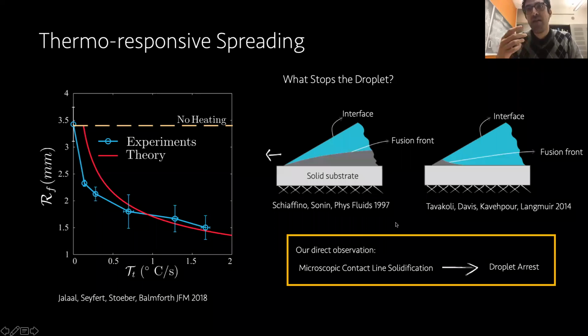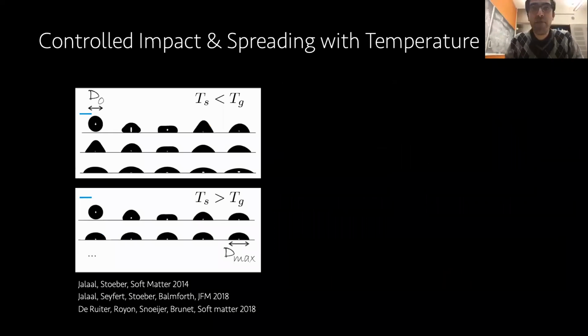So here, for some of the first time, we actually presented direct experimental observations of what happens. What we saw is what stops the droplet in this regime that we are talking about is this microscale contact line solidification. That's enough to arrest the droplet while it spreads. The same thing works for an impacting droplet.